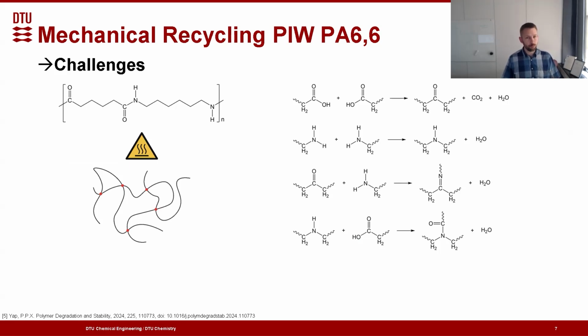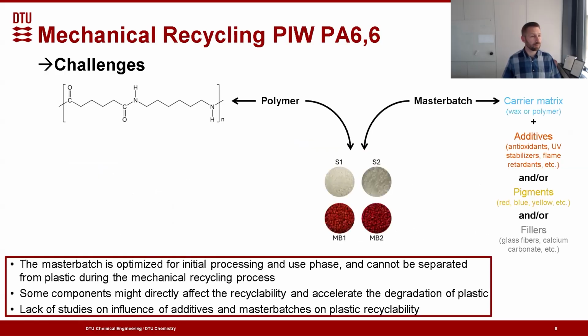A lot of things are done to suppress these things, and one of the most commonly used approaches to this is that you use additives and stabilizers. So what you normally do in the industry is that you combine this nylon with master batches containing additives, antioxidants to protect the polymer, stabilizers for processing stabilization, flame retardants if necessary, UV stabilizers and other things. This master batch typically comes with a carrier matrix, which can be the same polymer as the one that we're using for the base resin, but it can also be other polymers.